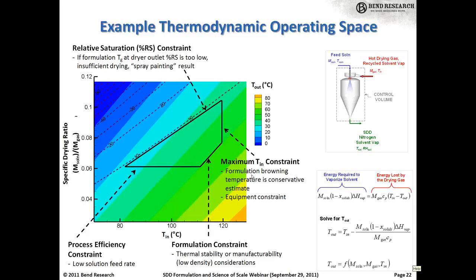You can look at a maximum inlet temperature constraint where it could be as simple as an equipment constraint. Your heater simply can't operate above a certain temperature. Or you may want to keep that below the browning temperature of the spray dry dispersion you're working with. And that could be identified with offline hot bench experiments, such that if there are any deposits within the dryer, you know that all of the metal is held at temperatures that are below the browning temperature of the spray dryer.